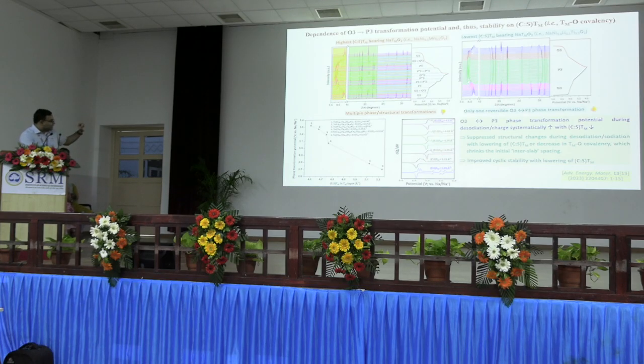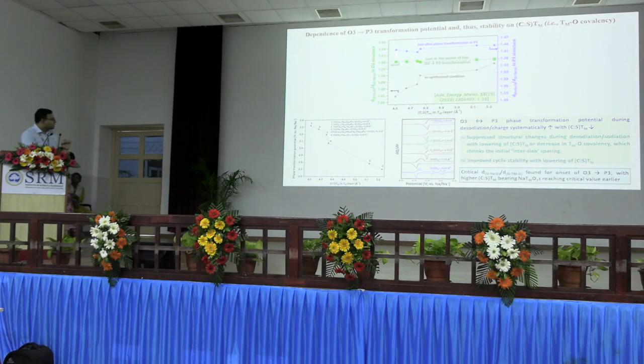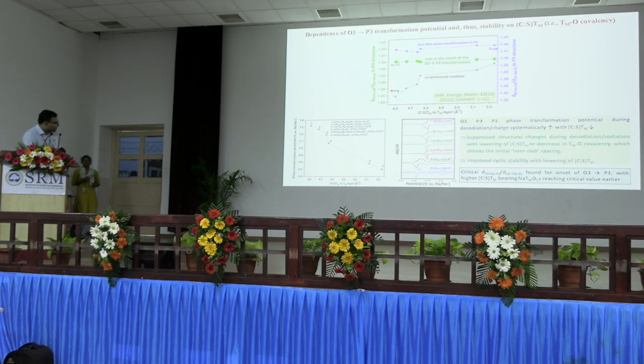Now when we looked at the synchrotron XRDs very carefully, we figured out that there seems to be a critical ratio between the interslab spacing and the slab thickness at which the onset of the O3 to P3 phase transformation gets initiated. For the materials with lower charge to size ratio, the initial ratio of the interslab spacing to slab thickness is far below that critical ratio. So one can pull out a lot of sodium before this transformation gets initiated, and so one can suppress the further transformations, as opposed to these where a little bit of sodium extraction will initiate the O3 to P3 phase transformation, and there will be a host of other phase transformations taking place, making the material absolutely useless over long-term cycling.